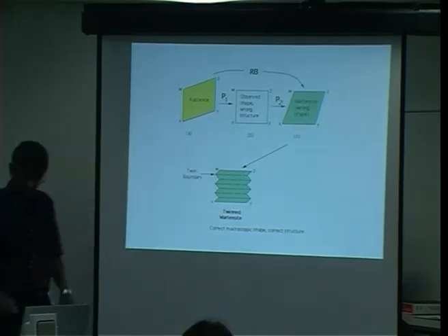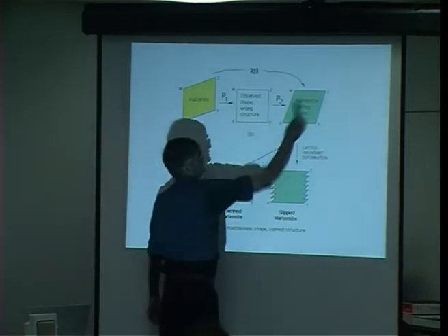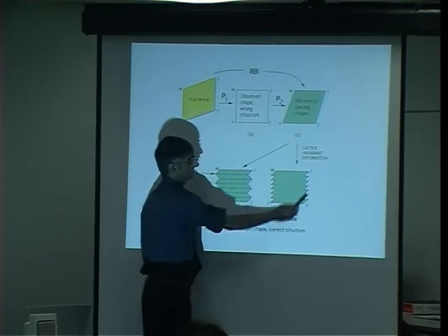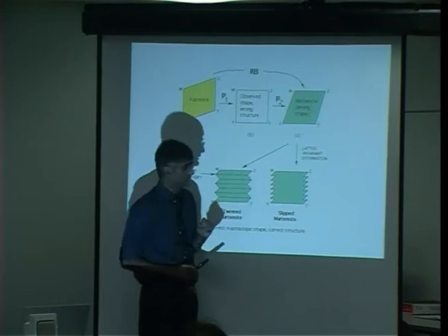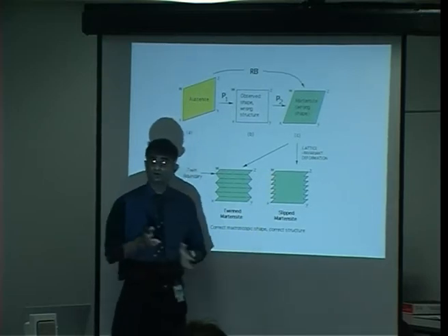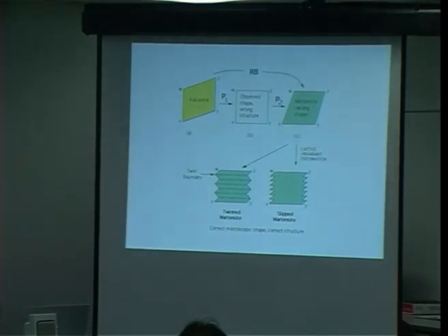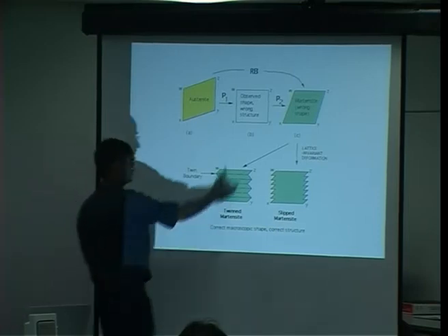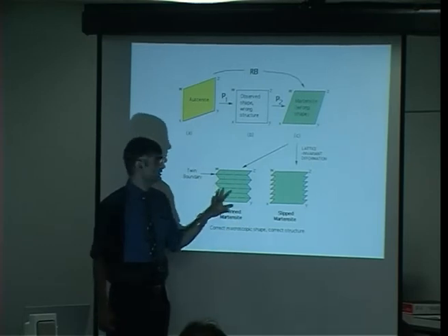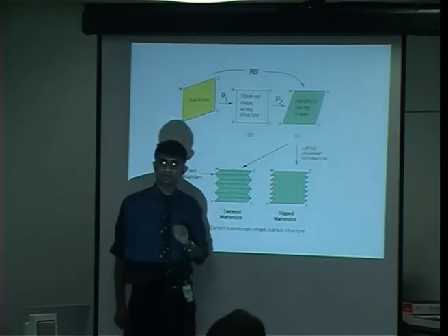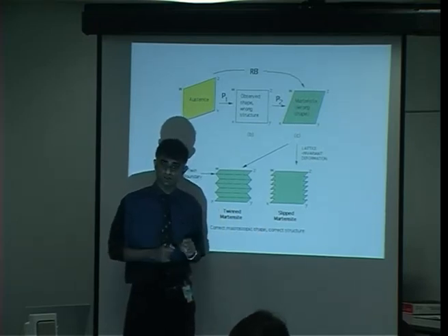Similarly, I could accomplish this using slip. So I could deform this heterogeneously until its macroscopic shape is that. Again, these facets here are rational planes, but this could be anything depending on how much deformation I need to add. And then the complete problem is solved. And the reason why we want the macroscopic shape to be like this instead of like this is that this greatly reduces the strain energy compared with an invariant line strain. So macroscopically, it's behaving like a shear deformation. Microscopically, it's actually an invariant line strain.